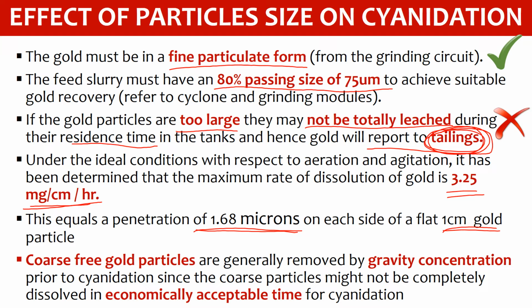Instead of taking a very large particle for your leaching process, we said it's better to take very small particles of your concentrate or your ore to the leaching process. So what do you do with these large sized gold particles? If they are free, coarse gold particles, then you need to remove them using your Knelson concentrator or your Falcon concentrator.